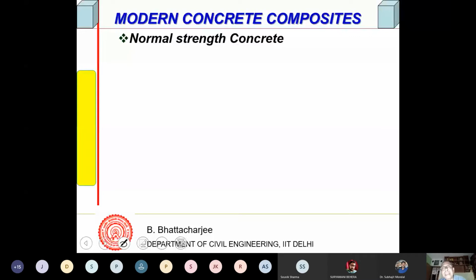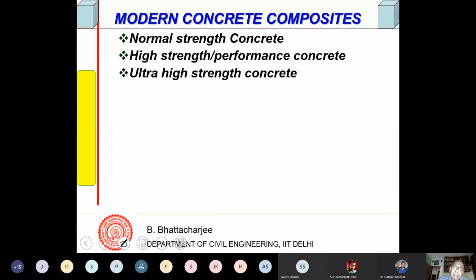Then you can have high strength or high performance concrete, which till the 1970s the strength was only up to 60 MPa. At best you could get up to 50 or 60 MPa, not more than that. Then you started getting higher strength, so we call it high strength concrete, from the 80s onwards, and then high performance concrete, ultra high strength concrete, reactive powder concrete. There are several of them.